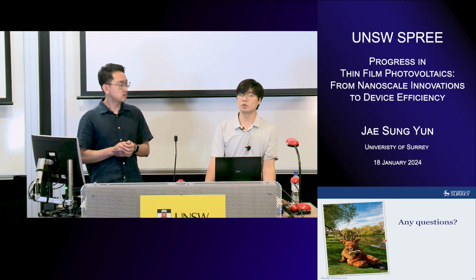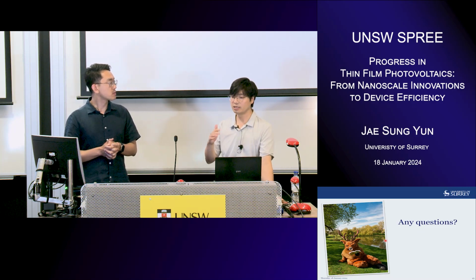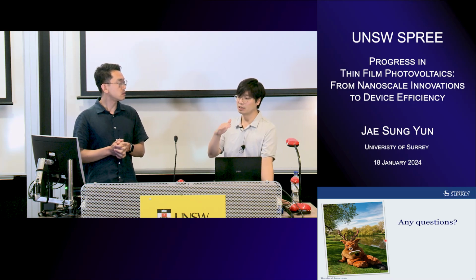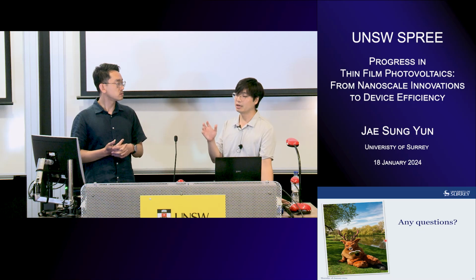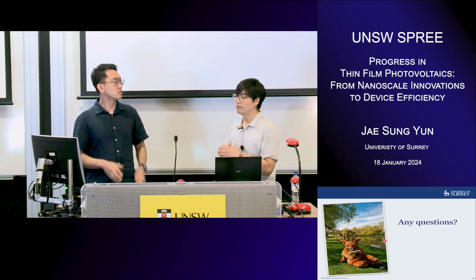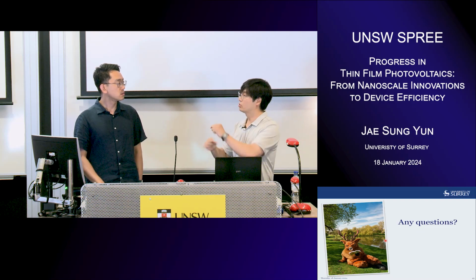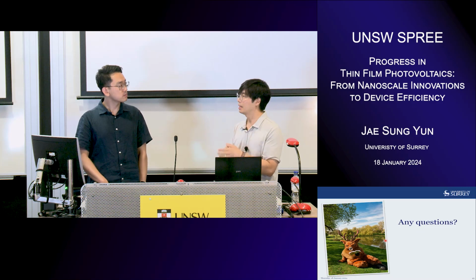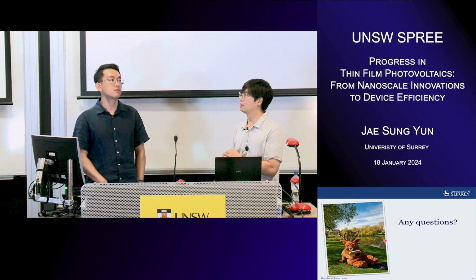There is. If you see the cross section, you can see there's an interface. However, in halide perovskite, the ions move very actively, so they form sort of one layer instead of two separate layers. So I think it can work if your material has a very high crystallization rate, growth rate, and halide migration. Okay.